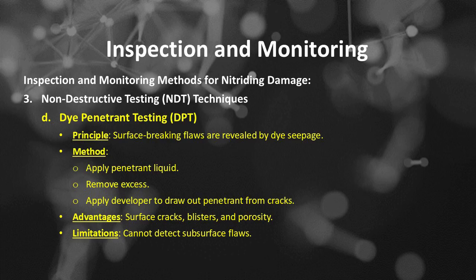The next NDT technique is dye penetrant testing, or DPT. The principle of DPT is that surface-breaking flaws are revealed by dye seepage. The method of DPT includes applying penetrant liquid, removing excess, and applying developer to draw penetrant out of cracks. The advantage of DPT is that it finds surface cracks, blisters, and porosity. The limitation of DPT is that it cannot detect subsurface flaws.